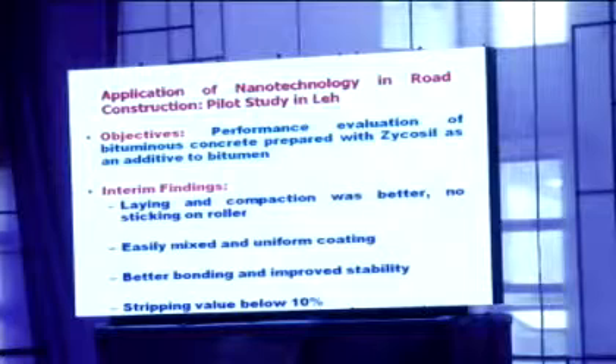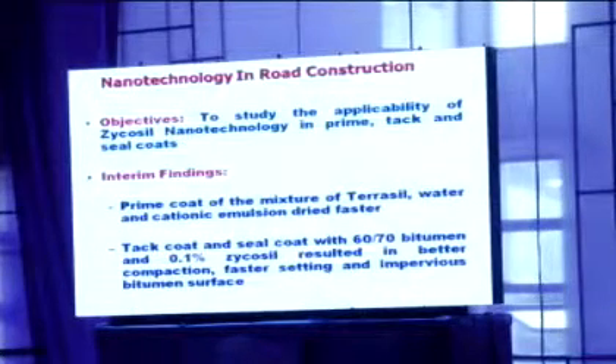Next is application of nanotechnology in road construction, a pilot study in Leh. Yesterday we saw a presentation from Zydex Industries, and the same materials have been reported in 2-3 projects. It was tested in a test section in Leh, and findings have indicated that laying and compaction was better. There was no sticking of the material to the roller when you use Zycosil as an additive to the bitumen. The mix can be easily mixed, and there is a uniform coating of the aggregates, better bonding and improved stability of the mixes, and stripping value has been observed to be less than 10%.